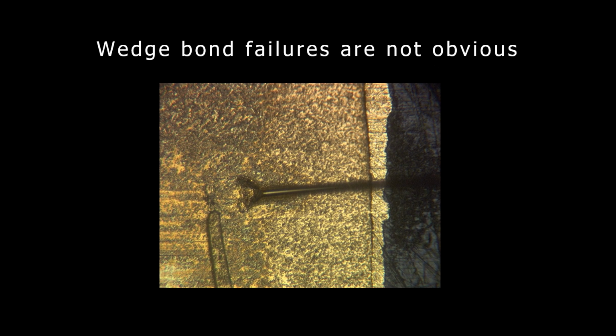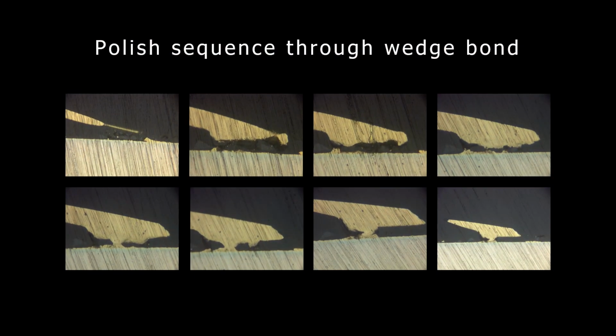This wedge bond failure occurred under the wedge bond and is only visible in cross-section. These photos were taken throughout a polishing sequence. We can see that the wire bond has lifted and is making intermittent contact in only a few places.